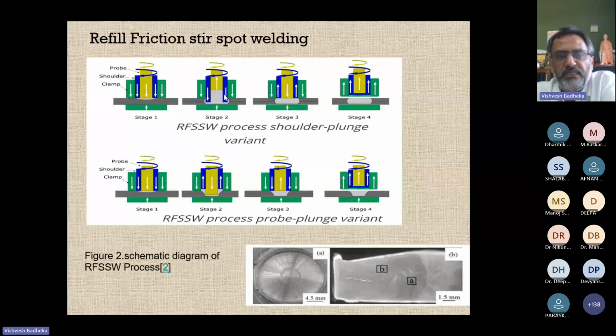You can see the motion is opposite, right? The clamp remains in the same situation. The whole intention of the green is to clamp the sheets, right? So they will remain the same. But in stage 2, you see the shoulder is moving down, the pin is going up. You can see the deformed material. Can you see the deformed material here, right? Because since the shoulder is going down, the material is deforming, and that material is pushing in the upward direction.